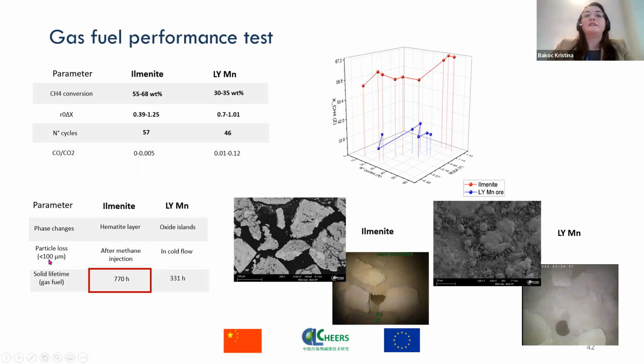So very fine particles, less than 100 micrometers, would be collected only after the fuel injection in the case of ilmenite, while for LYMN, they would be noticeable already in cold flow, so when only fluidization is achieved. This also leads, it seems, to a longer lifetime in circulation for the ilmenite, which under the gas fuel was around 770 hours. And I would have to specify here that the lifetime under petcoke injection, so under solid fuel, is about twice as high because we have a much lower reduction atmosphere. So based on this gas fuel performance test, ilmenite seems to behave better.